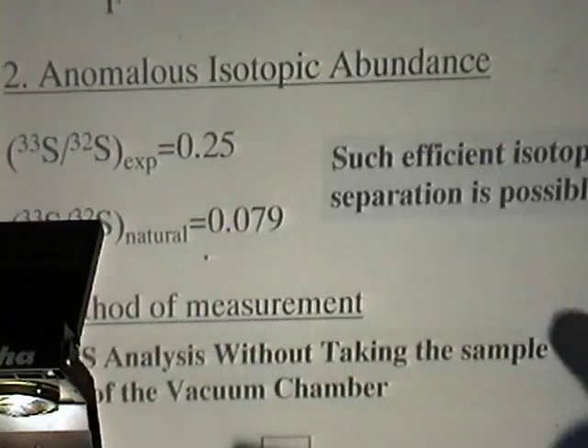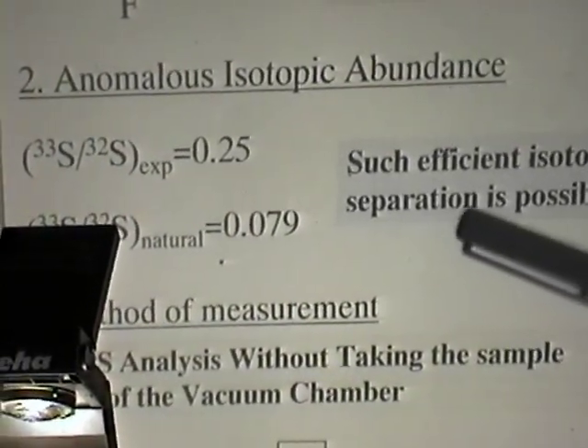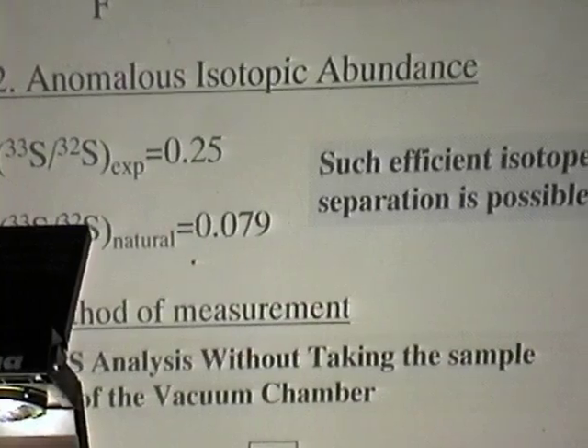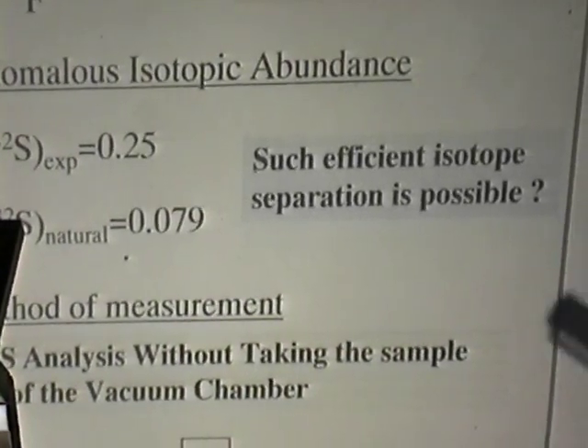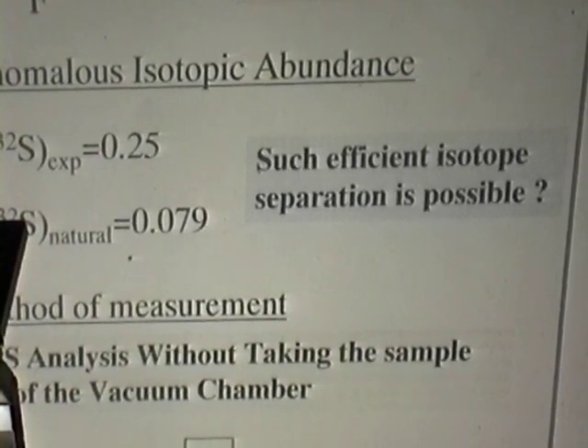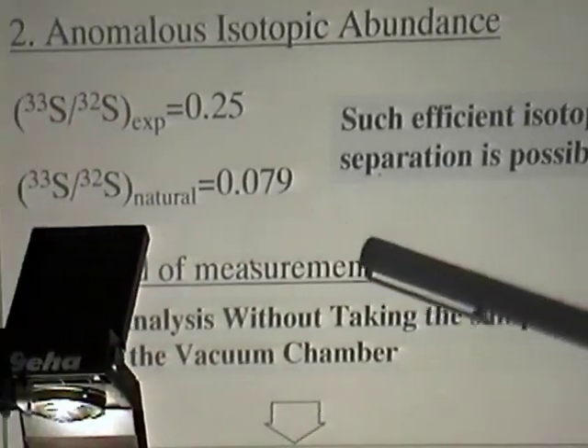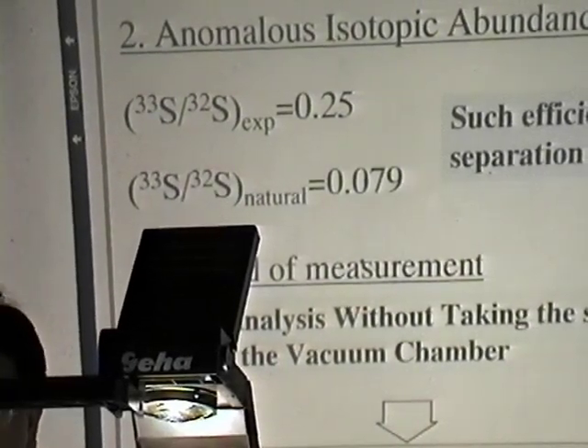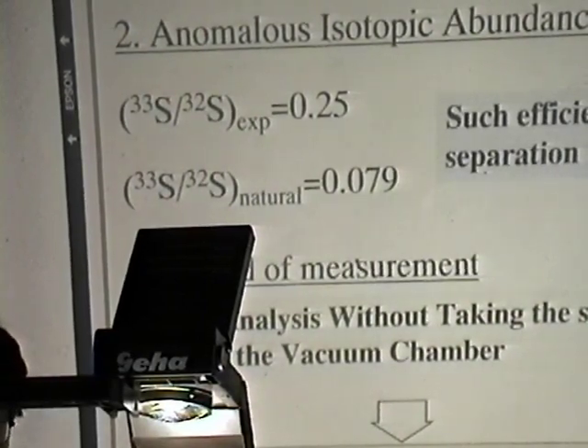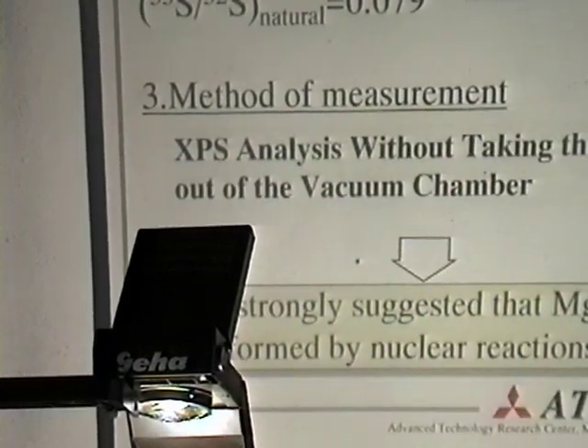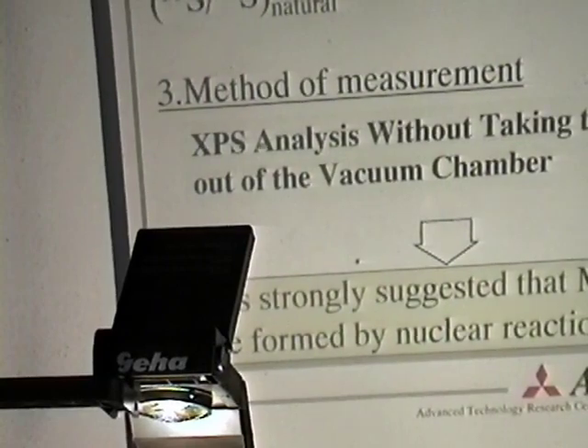Number 2, anomalous isotopic abundance. We obtain sulfur 33 by sulfur 32 equal to 0.25. Such efficient isotope separation is not possible by impurity. And number 3, method of measurement. We perform XPS analysis without taking the sample out of the vacuum chamber. So we think it is strongly suggested that magnesium, fluorine, and sulfur are formed by certain nuclear reactions.